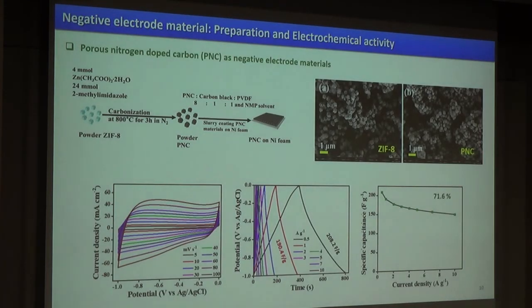Now for asymmetric device fabrication, we also need a negative electrode material, and for that purpose we use ZIF-8 derived porous nitrogen doped carbon materials, and then this material was slurry coated on nickel foam and studied in the 3 electrode configuration as a negative electrode material. These are the corresponding FESEM images of the ZIF-8, and this is the FESEM image of the derived porous nitrogen doped carbon, and this material in 3 electrode configuration showed nearly 190.4 farad per gram specific capacitance and also quite good rate capability as a negative material.